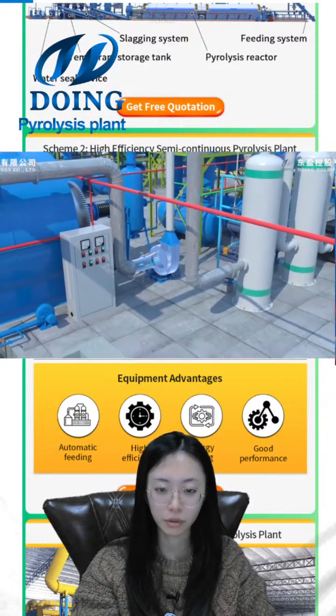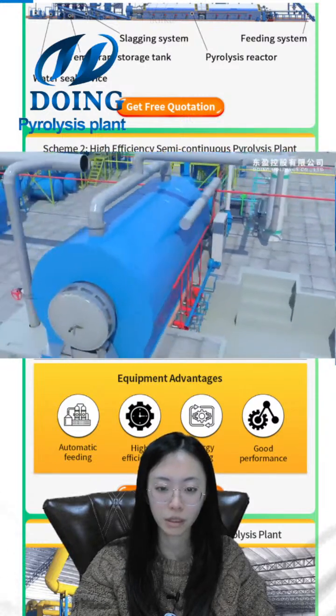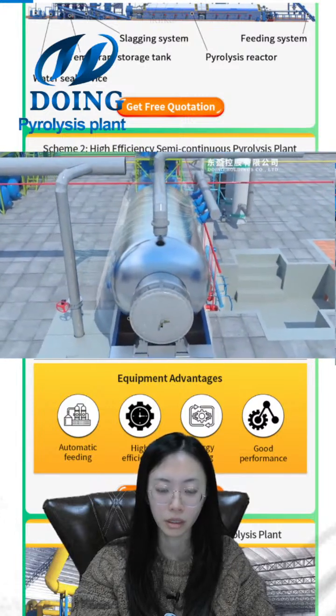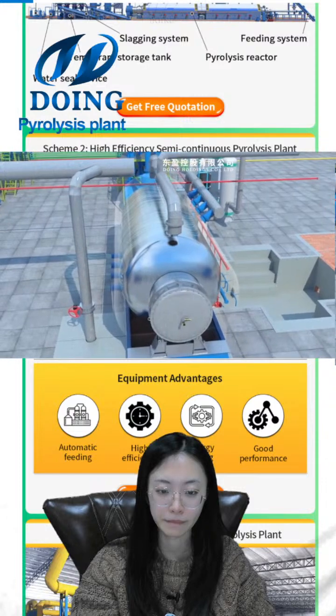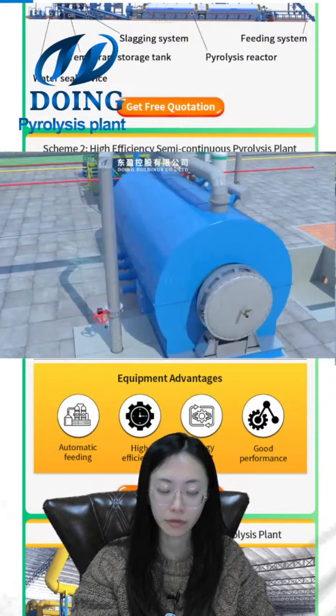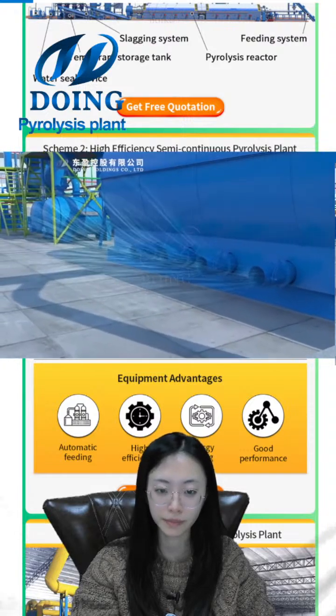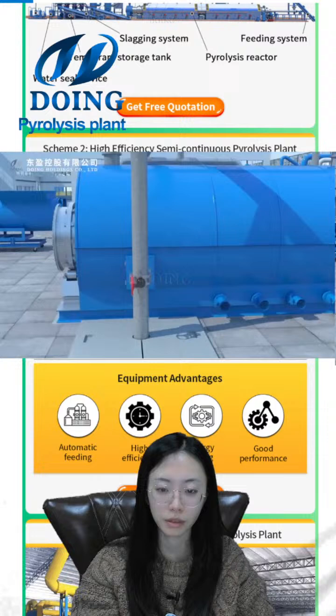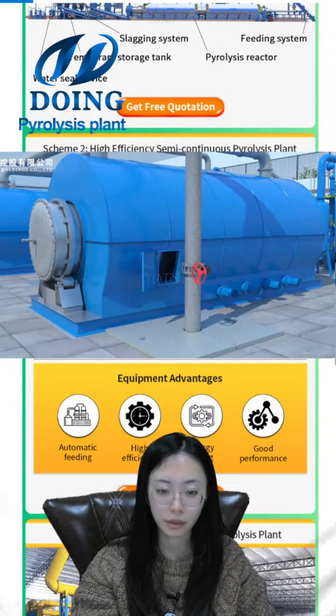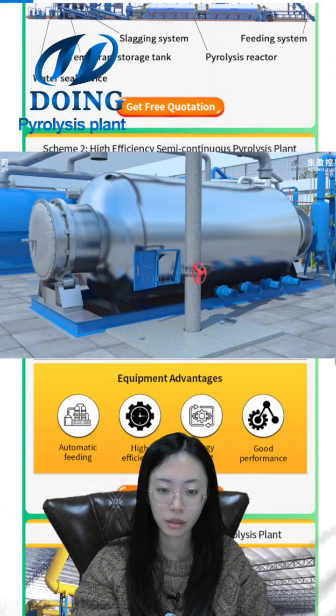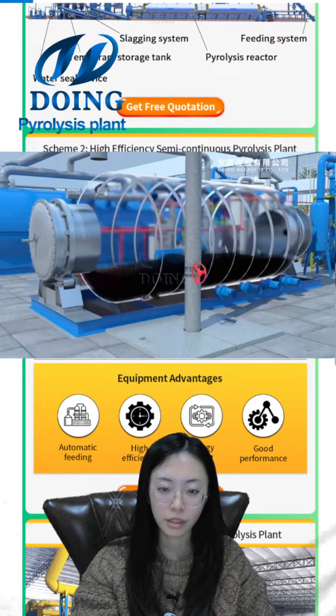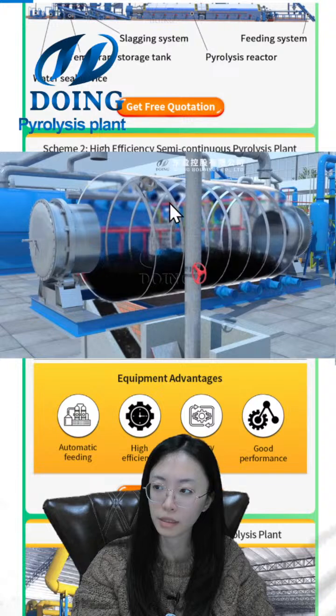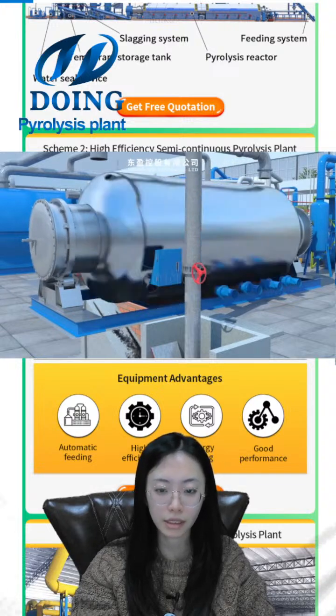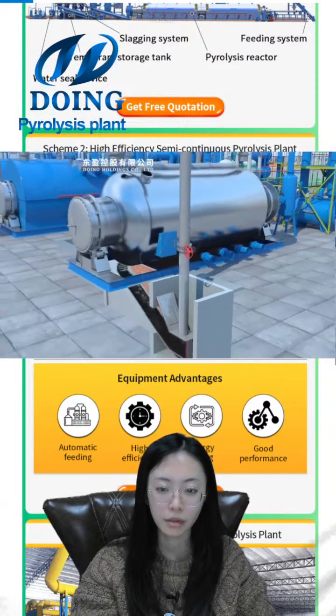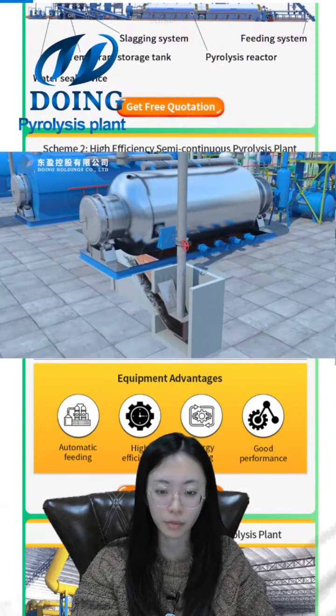An air cooling system cools down the reactor with a 15 kilowatt generator, which can save cooling time, shortening it from 8 hours to 4 hours. That will greatly improve the efficiency of production. After cooling, we come to the side discharging system to slag the carbon black. The side slag has 2 advantages. First, high efficiency. It can slag twice with 1 rotation and directly slag the carbon black to prevent it from flying and polluting the workshop.